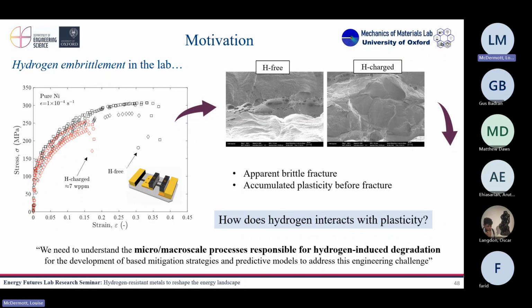And so if we see a brittle fracture there, then why do we see that we have still accumulated plasticity here? Okay, that's somehow a bit contradictory, and we cannot explain it with just one of the mechanisms that I explained before. So we really want to understand how hydrogen interacts with plasticity. Because it's really important to develop the models that then will be able to predict how a bigger structure is going to behave in, let's say, the middle of a hydrogen-rich environment.